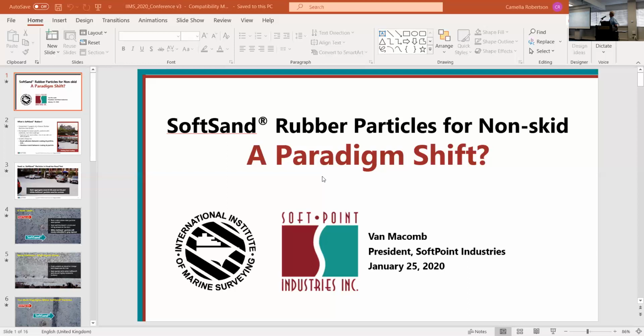So I went back 6 years later and took a look at this. Again, the white particles you see there are exposed soft sand after 6 years of traffic on this deck. All those little craters are where the sand aggregate had been and was ejected from the coating over time. So this is a nice little test case that we did up in Connecticut. There should be a little piece of sand on Roosevelt's temple on the dime there. Like I said, black craters are where the sand particles had been, and the white dots you see there are the tops of the soft sand rubber particles.